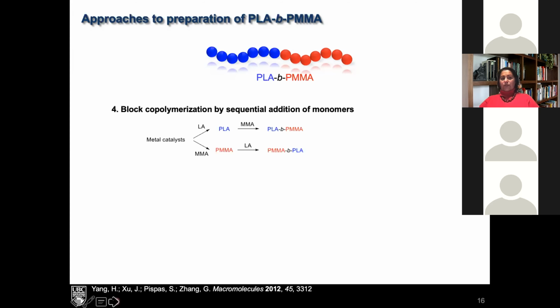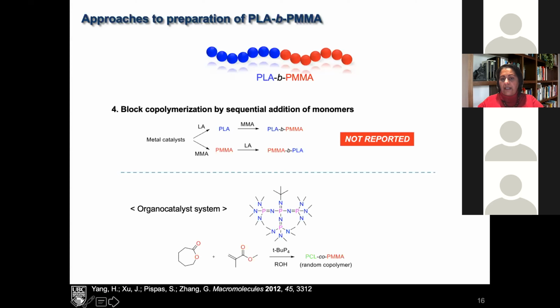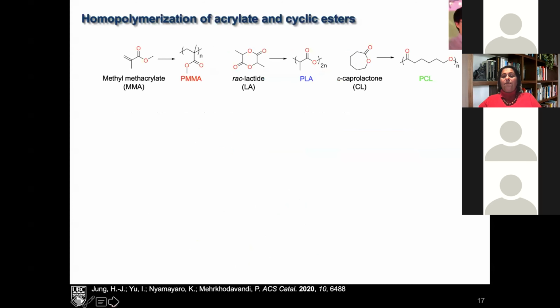Also, what we want to be able to do is something really simple. To have a catalyst that does exactly what I showed you in the previous segment. Add one monomer, polymerize it, add the second monomer, and form a block copolymer by simple sequential addition. And before our publications, this was not known. The only example of anything similar was this organocatalyst system with caprolactone and methyl methacrylate, which generated a random copolymer, which is not something that we need, because we want to have those two blocks to allow us to form the amphiphilic polymer to actually make the micelles and the superstructures.